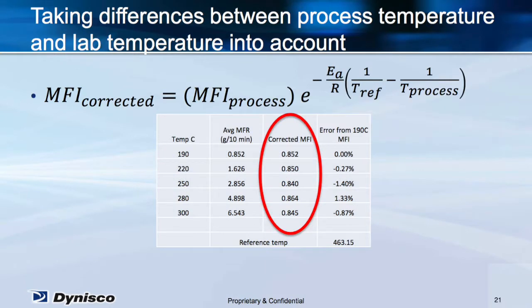With a little further mathematical manipulation of the Arrhenius equation, you can rewrite it in a form that is useful to correct the MFI for temperature. In the formula above, the only variables are the process temperature the material is actually run at, the reference temperature of the ASTM test, the activation energy, EA, for the material, and the MFI actually measured by the rheometer. In the table above, we take the melt flow index measurements that vary from 0.852 at 190 C to over 6.5 at 300 C and apply the correction. We find the corrected MFI is the laboratory reading of 0.852 within about 1.5% over a temperature range greater than 100 C. Is that good enough?